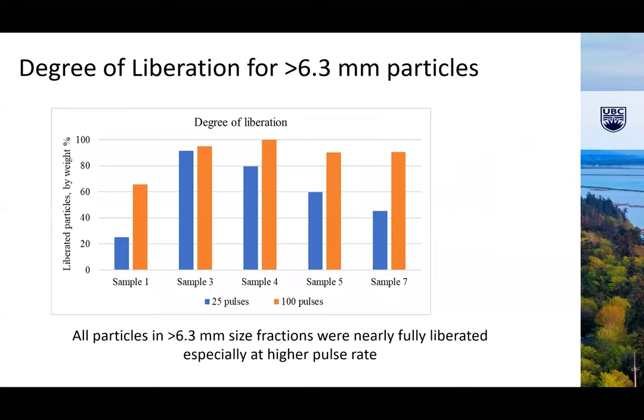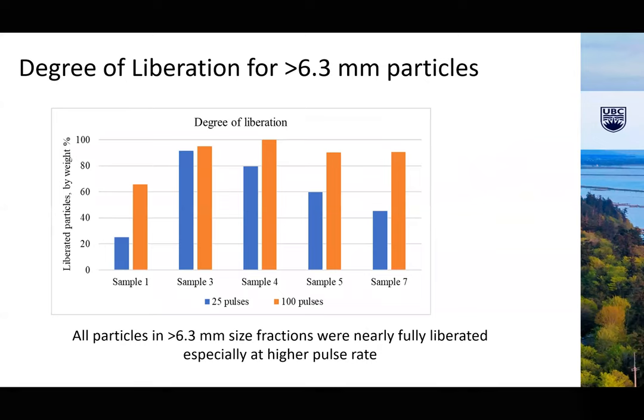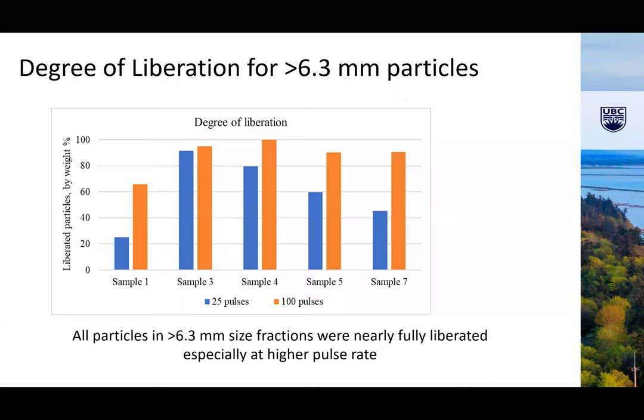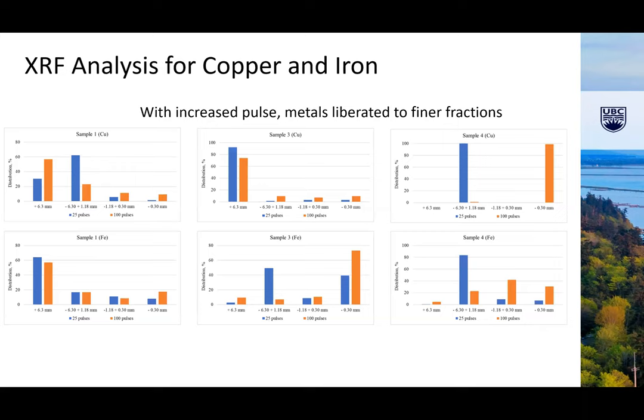We also did liberations. We estimated liberation in each of the samples after 25 and 100 pulses, looking at the material that was disintegrated. We look at the percent of liberation. So as you can see, all particles in this coarser fraction were nearly fully liberated, especially at high pulse rate. So that means this is a very good opportunity to get most of the metals in a liberated state.